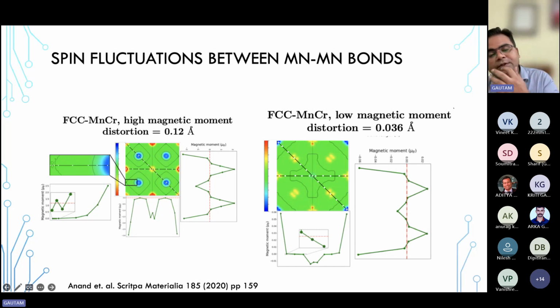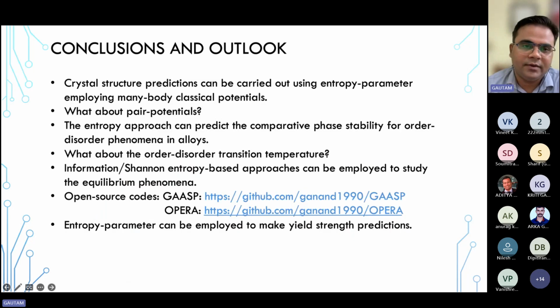So the spin fluctuations play a very crucial role in developing distortion. And this should be accounted for when one wants to calculate the volume change associated with an atom in high entropy alloys. Because this is just an impurity in a matrix, and these calculations are complicated. If you talk about high entropy alloys, this will be a further difficult calculation.